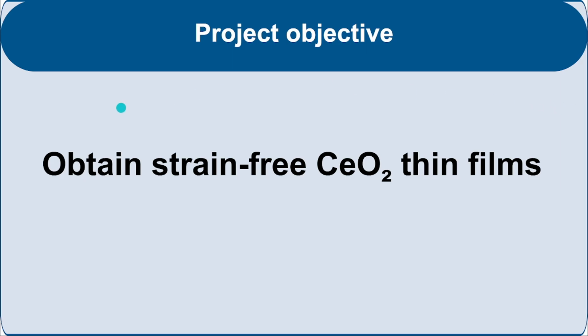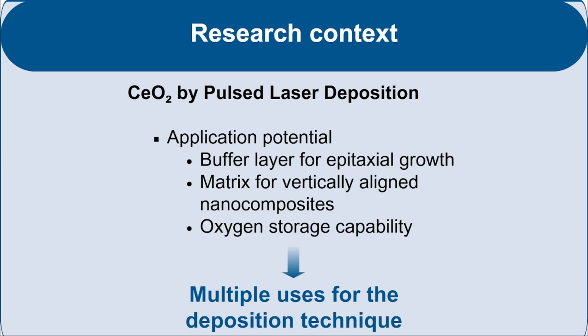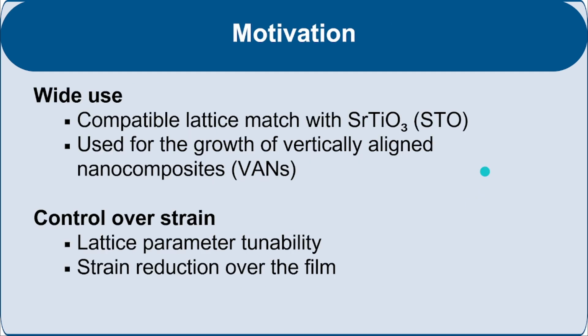The primary goal of this project is to investigate CeO2 thin films in order to develop a method for reducing their planar strain to zero. Our focus was primarily on the use of CeO2 in the Pulsed Laser Deposition technique, PLD, where it's used in several applications such as a buffer layer, matrix for vertically aligned nanocomposites, and it has a large oxygen storage capability. Therefore, we chose SrTiO3 (STO) as the substrate, owing to its compatible lattice parameter and its established use in the growth of vertically aligned nanocomposites (VANs) alongside CeO2.